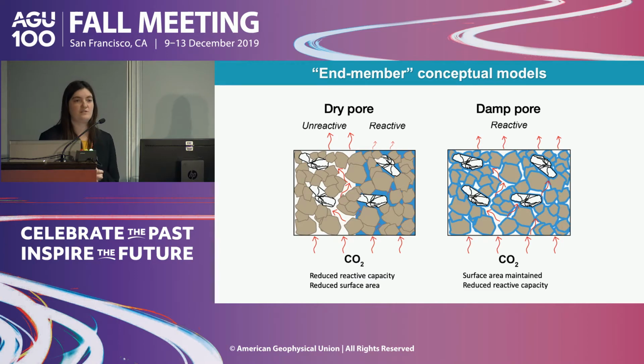And so we incorporated these two ideas into conceptual models that were implemented in Min3P. So one of these we call the dry pore model, which divides our porous medium into dry unreactive pores and wet reactive pores, the proportion of which depends on the water saturation. So in this case, we've reduced both the reactive capacity and the reactive surface area, as we've essentially removed part of the porous medium from being able to react.